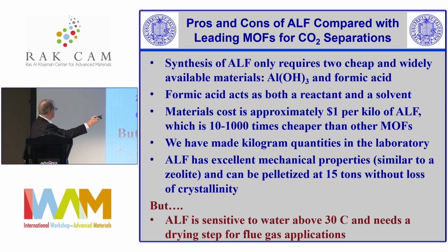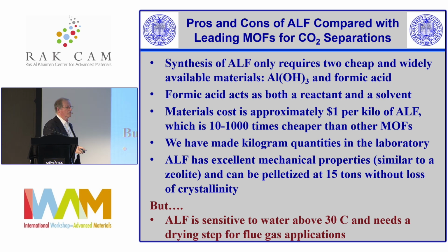Synthesis of ALF requires just two cheap and widely available materials, aluminum hydroxide and formic acid. You don't even need a separate solvent because the formic acid acts as the solvent. It also generates the CO2 that goes into the cavity, so you need an excess of it. The materials cost is approximately $1 a kilo of ALF. So it's incredibly cheap and obviously earth abundant. It's many, many times cheaper than other MOFs.